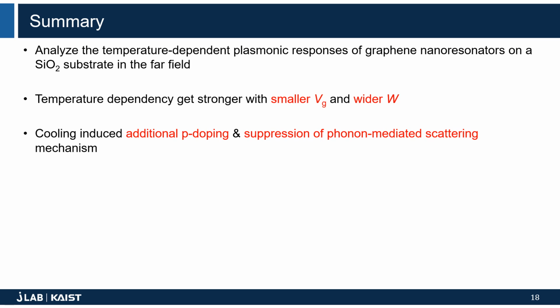To conclude, we have analyzed the temperature-dependent plasmonic responses of graphene nanoresonators on a silicon dioxide substrate in the far field. When the temperature drops, the temperature dependency gets stronger when the gate voltage is smaller and the resonator width is wider. The increase in graphene plasmon peak intensity can be attributed to the cooling-induced additional p-doping and suppression of phonon-mediated scattering mechanisms at low temperatures.